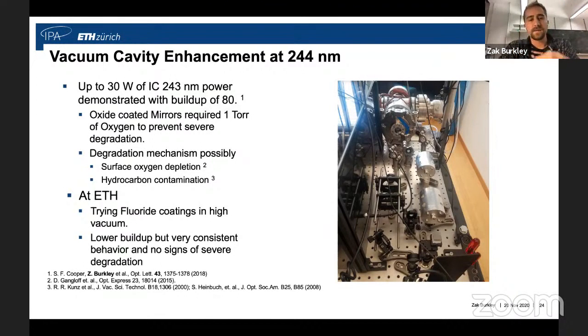And this degradation mechanism is possibly due to surface oxygen depletion, which is helpful for having the oxygen in there, or hydrocarbon contamination, which can also be avoided if you have the oxygen in there. The oxygen interacting with the UV actually is somewhat of a cleaning mechanism. So at ETH, what we're trying though is some fluoride coatings. So if we have a calcium fluoride coating on a fluoride substrate, hopefully we can remove the surface oxygen depletion. And what we've seen so far with these fluoride coatings is that the buildup is a little bit lower than the fused silica, but they have very consistent behavior.